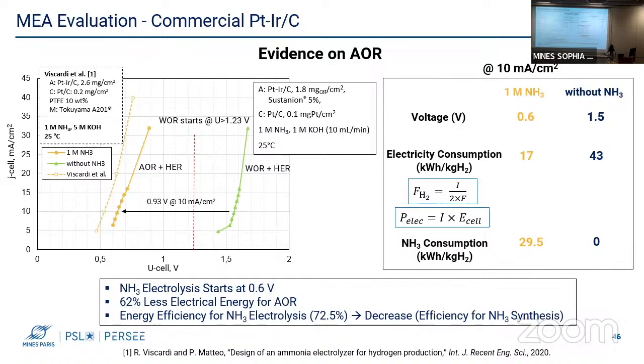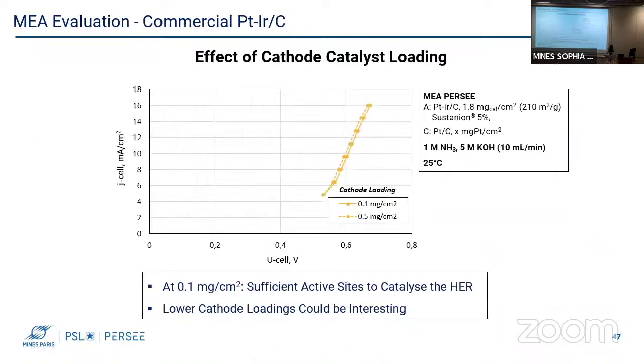By comparing our data to the literature, they were quite close. However, room for improvement was still available due to the differences in the operating conditions used. For this, we decided to study the impact of several parameters. We start first with the cathode loading, and we change this loading from 0.1 to 0.5 milligram per centimeter square.